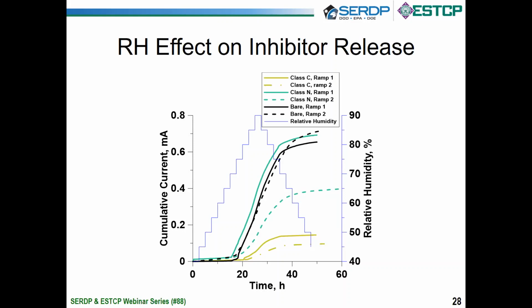So this points out a couple of important things. And the first is that it takes time. There's a number of different kinetic processes that are going on here. First, there's the time for moisture to get into a coating system. Then there's the time for those inhibitors to be liberated and get out to an unprotected place. And then there's the effectiveness of the inhibitor. So in the case of a chromate, where you barely need any chromate to protect the scribe, in the first cycle you see a major effect. For the non-chromes, because they're less effective inhibitors, you need more time.